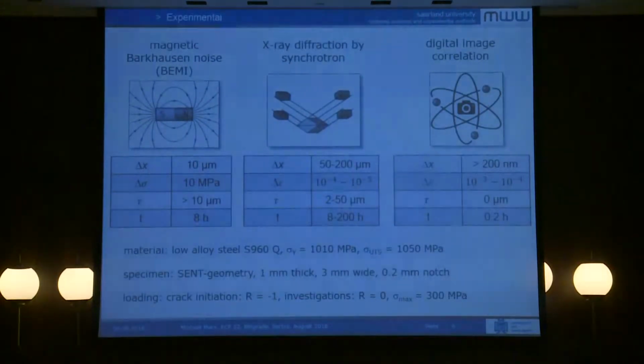and this is what we have investigated. We have used three different techniques: magnetic Barkhausen noise, X-ray diffraction in synchrotron, and digital image correlation. Every technique has an advantage or a disadvantage. Here, for instance, we have a very high spatial resolution, and it's quite fast. However, we only see what happens on the surface and not inside the specimen. And with other techniques, we can look at least a little bit inside our specimen to compare it.